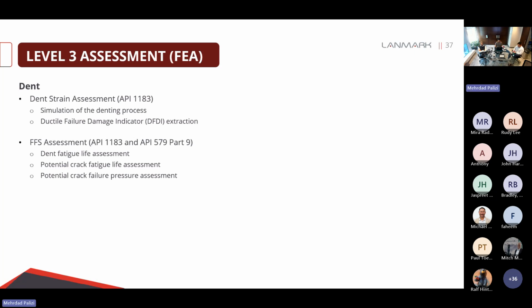So next, I'm going to talk about the level 3 assessment for dents. In the case of dents, we have 2 main steps. The first step is dent strain assessment. Basically, we want to have a quantification for the amount of damage in that indented area, the time that we had the indentation. And actually, the second part is doing FFS assessment. This is going to be for the fatigue failure for the dent. If in the first step, we got like a severe dent, then probably we're going to have crack inside that dent, and we should kind of be mindful for the fatigue life and failure pressure of that crack.